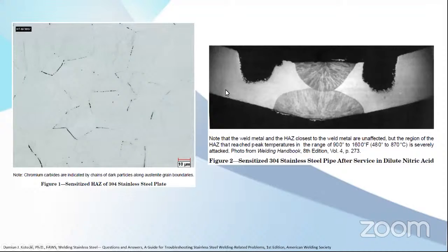So let's see the microstructure. And this is for 304 without L, so this is not low carbon. You can see the black lines on the grain boundaries. So this is the chromium carbides, and the corrosion will start on the black area.